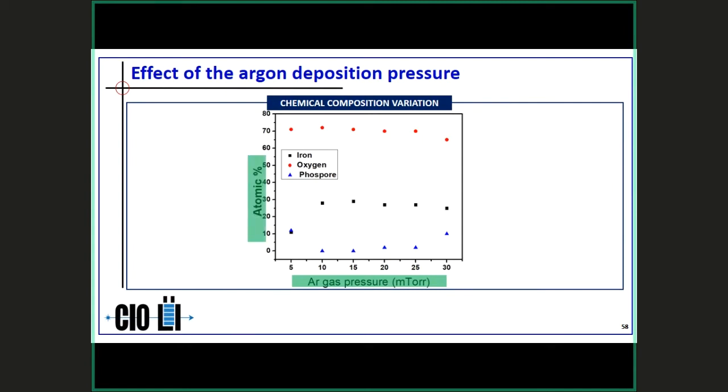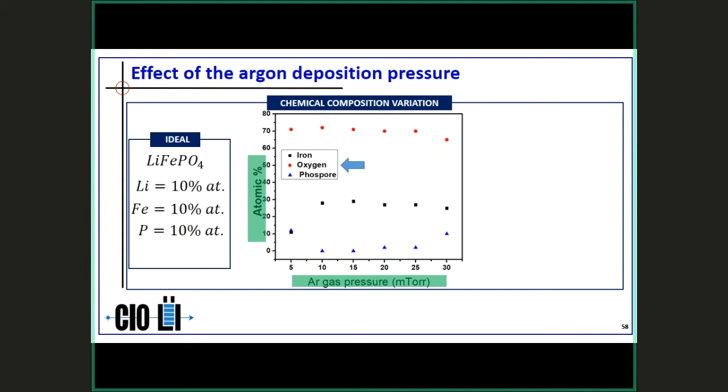The y-axis presents the atomic percentage of the elements. Which elements? Iron, represented by the squares; oxygen, the red circles; and phosphorus, the blue triangles. They are based on the chemical formula of lithium iron phosphate. What is the ideal value that we are looking for? We are looking for an iron atomic concentration of 10%, and the same value is true